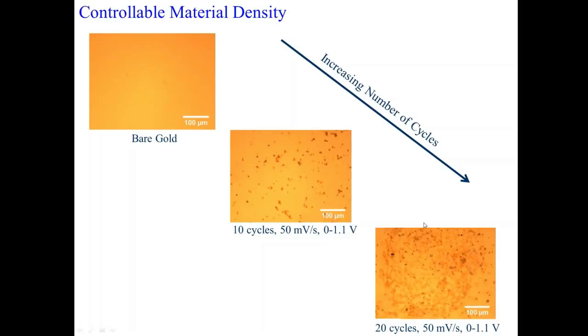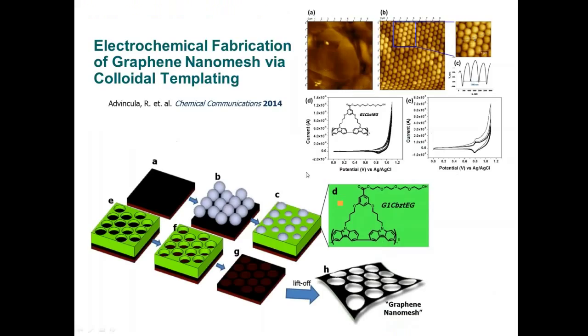So this chemistry actually allows us to do what we call nanomesh fabrication. If we take the colloidal templating method, we can modify the graphene oxide surface and deposit, let's say, this Carbazole unit, then remove the templated structures and delaminate it from the surface. In principle, we can end up with a freestanding graphene nanomesh film that is ultra thin.